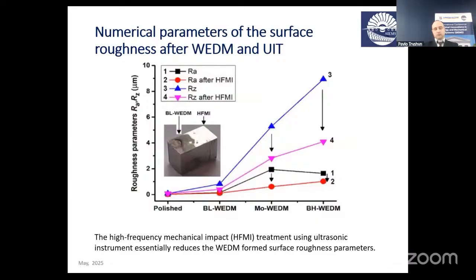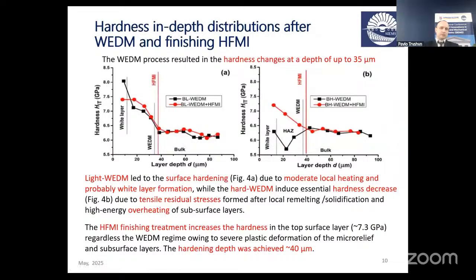Here on this slide, you can see the numerical parameters of the surface roughness. Again, we see that compared to the polished sample, the EDM process increases the roughness, and the following surface modification by finishing treatment using the ultrasonic instrument essentially reduces it. We can observe the hardness changes using the indentation method, and it is shown that the hardness changes occur at depths up to 35 micrometers. After the light regime we have some hardening, while the hard regime results in softening of the surface layers, and the finishing HFMI process can restore the hardness and even improve it.